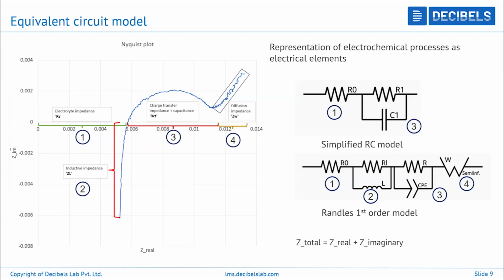Okay, so again, to further talk about the diffusion processes itself, it depends upon what kind of diffusion happens. Whether you're talking about idealistic diffusion or non-ideal diffusion, it depends. So there are classifications of diffusion itself. Maybe you are seeing something that is marked here as semi-infinite. So semi-infinite diffusion is basically, it talks about the distance of diffusion, basically the thickness of the electrodes, either the anode or the cathode, within which the ion is undergoing diffusion, and whether it is an infinite thickness or semi-infinite thickness or limited thickness. Based on that category, we can categorize the Warburg element here.